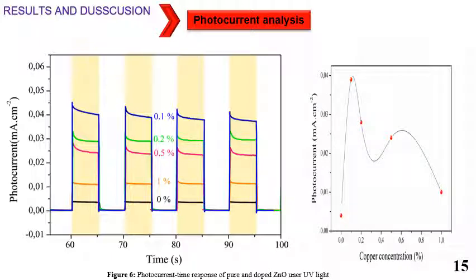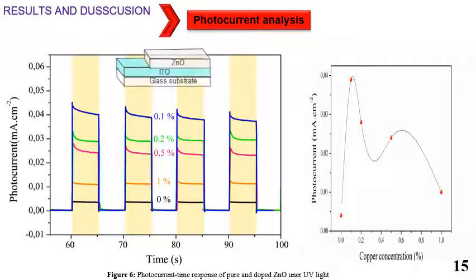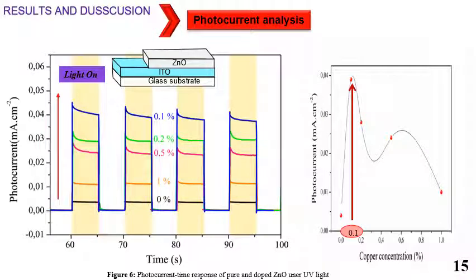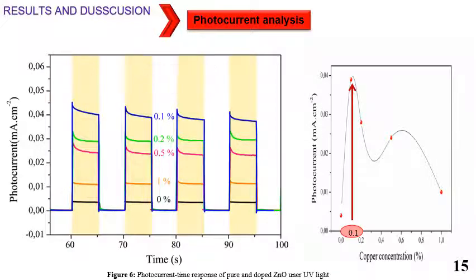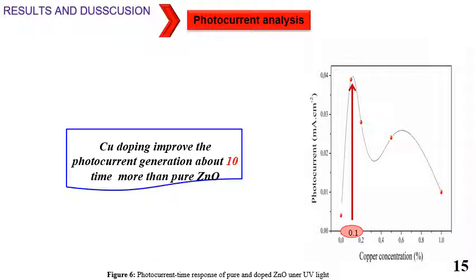Solar cells are applications based on the excitation of electrons in a semiconductor material using a light source. Thus, in this part, we present the photoelectric response, under illumination and without illumination, of our films by photoelectrochemical study. As shown, under UV illumination, the photocurrent response showed a tendency to increase through the contribution of copper doping, where the improvement was more than 10 times greater for samples doped with 0.1% compared to pure zinc oxide.